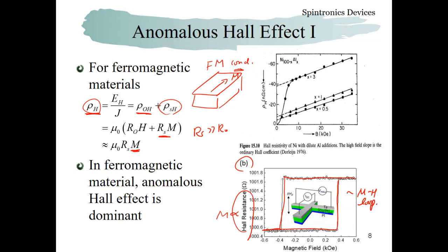So we can measure it for a very thin film, where typical measurement of the magnetic moment is not easy because the total magnetization is not so large. But this transport measurement, or Hall measurement, gives us the shape of the MH loops. In this measurement, we can obtain the coercivity very easily. And you can see the shape of the loop is quite like the Stoner-Wohlfarth model result. So it behaves like a single domain.